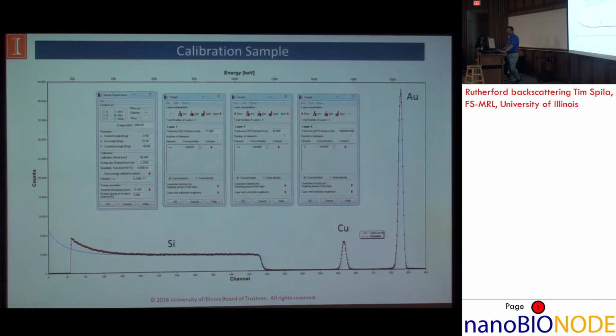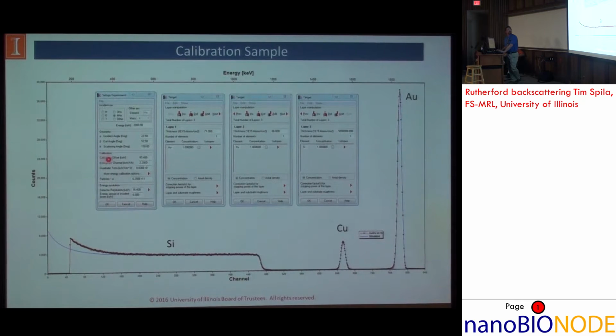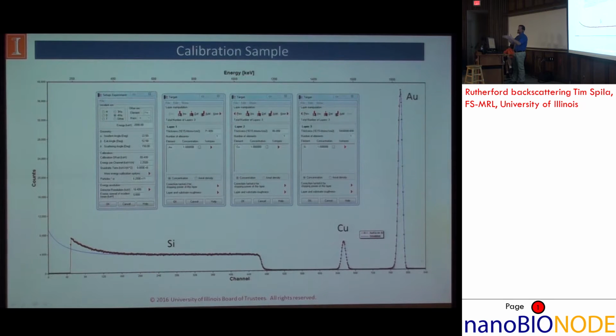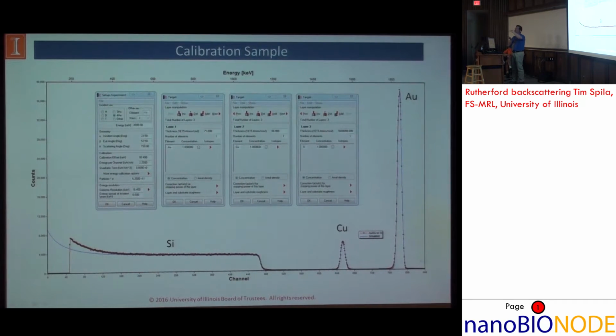So basically how this beam, the sample, and detection angles that we use. And also we have information here on the calibration offset, energy per channel, and particles times solid angle in steradians. That's where the calibration really comes in useful, because it allows you to get a first handle on the calibration offset and energy per channel. So basically, how do we calibrate our x-axis? And then the particles per steradian helps calibrate our y-axis, although that one changes based on how long you're taking your measurement for.